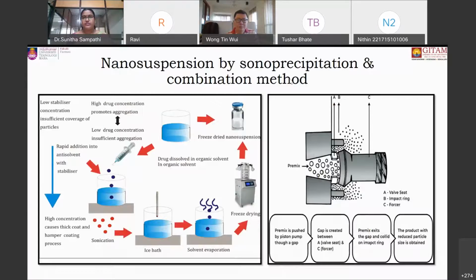Here we have prepared the nanosuspension by a simple sonoprecipitation technique, where we dissolve the drug in the organic solvent, followed by addition of the organic solvent into the aqueous stabilizer, then subjecting it to sonication and complete evaporation of the solvent, and then freeze drying the product to get a freeze dried nanosuspension. In the combination technique, as reported by Lee et al., the combination technique always gives us a low particle size. So after precipitating the drug into the aqueous stabilizer system, we subjected it to a roto-evaporator to completely evaporate the solvent, and then to a high pressure homogenizer at different pressures as well as different cycles.